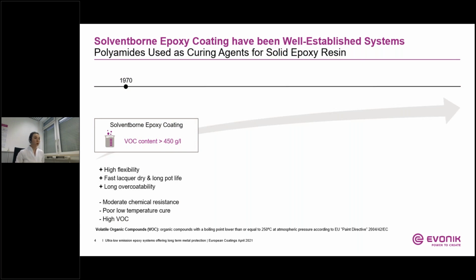Okay, allow me to show you how the market trends have impacted the epoxy coating development over years. Since the 70s, solventborne epoxy coatings have a successful track record. Here, typically, polyamides, along with solid epoxy resin, have been used for heavy-duty metal protection. The long-chain fatty acid backbone of polyamides provides a good combination of corrosion resistance, flexibility, and adhesion. However, polyamide curing agents are often high in viscosity and provide limited solvent and chemical resistance. Another limitation of this technology is poor low-temperature cure performance. Typically, polyamides remain sticky when cured at lower temperature.